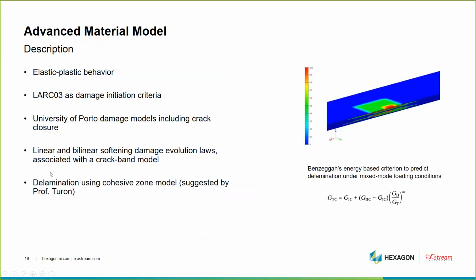Another feature of this model concerns the delamination. So in this case, delamination is handled using a cohesive zone model, cohesive zone elements. So it's based on cohesive elements, and we use the Benzeggagh-Kenane energy-based criterion to predict the delamination under mixed mode loading conditions. So here, what we have coded is simply the framework that has been proposed by Professor Turon from Girona University in Spain.